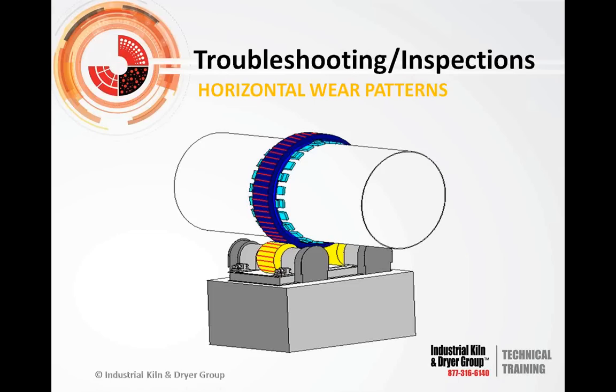Another common type of wear pattern is if you see horizontal lines across the surface of the tire or roller. We call these timing marks, and typically if you look at the spacing of these marks, sometimes they'll show up as very faint lines across the tire and rollers. They'll show up initially as faint marks. I've seen them as deep as an eighth inch, and the unit is bouncing all over the place. But typically when you're first looking at this, if you see these faint horizontal marks and they're about the size of the tooth thickness on the gear, the most probable cause is that the gear is starting to bottom in the pinion and it's starting to vibrate. So you're getting enough of a transfer of that vibration from the gear that it's transferring into the tires and rollers.